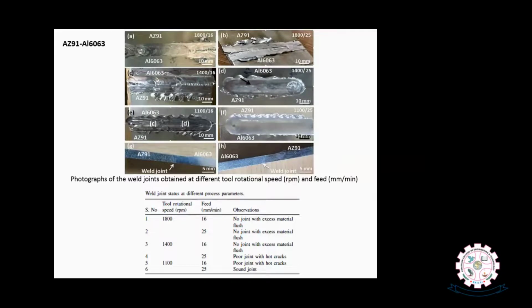And most of the defects which were observed in the joints of magnesium alloy and aluminum alloy are, you can see here in this illustration, excess material flush and hot cracks. So these are the common defects that we observe when we try to join magnesium with aluminum using the friction stir welding process.